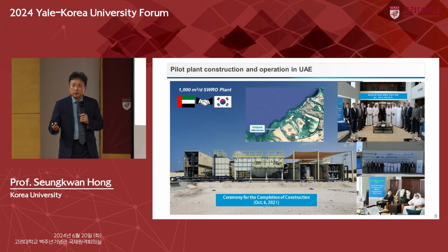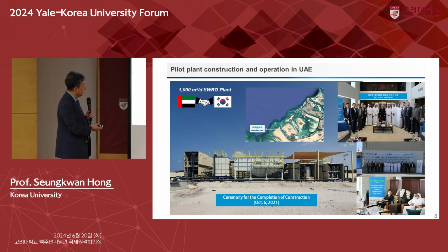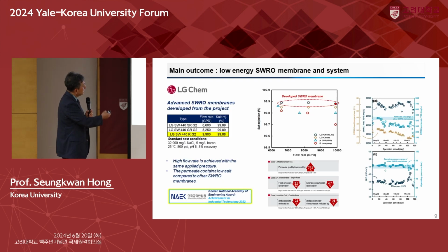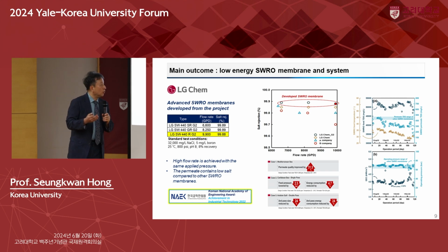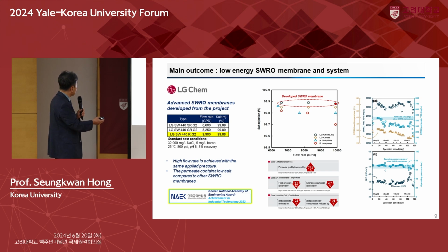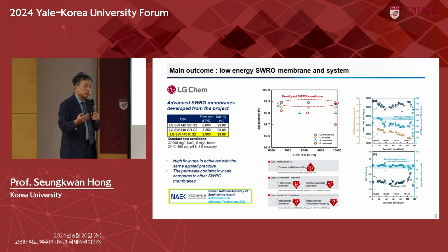Because of COVID-19, we experienced a very difficult period designing and constructing this pilot plant. However, we were able to finish this pilot plant in 2021, and then we operated it for 1 year. Here are some of the main outcomes. LG Chem developed low energy SWRO membrane modules, and while maintaining a flow rate of 9,900 GPD, salt rejection is maintained at the highest level. That is very difficult to do. When you increase productivity, you actually compromise salt rejection. However, the LG membrane was developed to achieve high productivity with reasonable world best salt rejection.